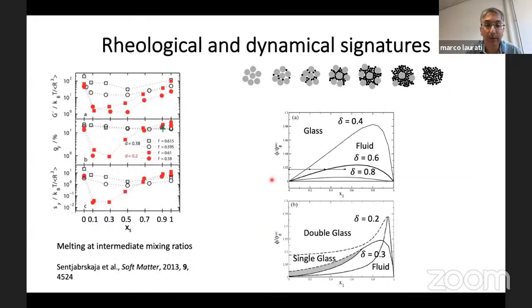So actually, at that time, we were mostly interested from our experimental side in investigating the rheological properties of these glassy binary mixtures. And therefore, one of the studies that we did at that time was investigating along a line in which we kept the total volume fraction of the system constant, and we increased the amount of small spheres in the system. So studying how the rheological properties were changing. And of course, this gave us already signatures of what happens in the phase behavior of these systems.